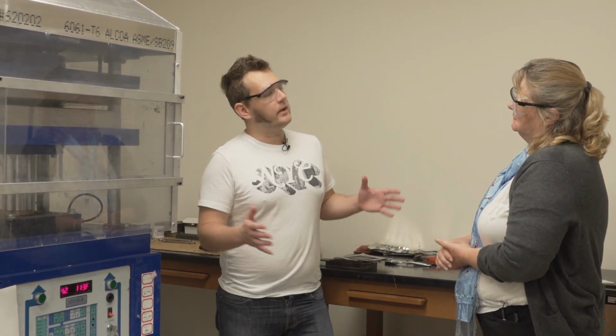So with a press like that, how big could you make an aerogel monolith? Yeah, so the restraining force you need is basically the area times the pressure you want inside your mold. We need to get above about 2,000 psi to go supercritical. 1,300 really, but we usually go to about 2,000 psi in the mold. So it scales with area. In theory, we could make a large aerogel if we had a large enough hot press. But there are some issues with diffusion, and when you release all the supercritical gas.